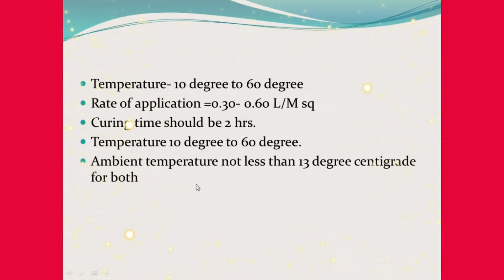Temperature 10 degree to 60 degree. Rate of application, that is 0.30 to 0.60 liter per meter square. Curing time should be 2 hours. Temperature 10 degree to 60 degree. Ambient temperature not less than 13 degree centigrade for both.